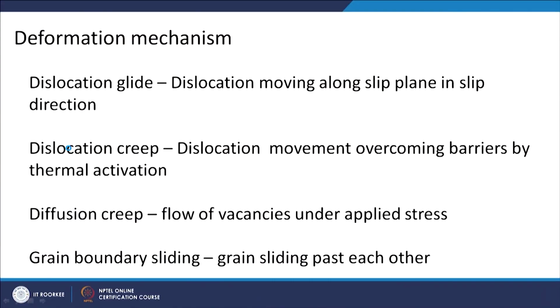Deformation mechanisms, we already have. These are the typical deformation mechanisms which take place during high temperature deformation. What we usually get at room temperature or low temperature is through dislocation glide, where the dislocation generation will take place. Then the dislocation will glide on the slip plane in the slip direction. So, this is your usual dislocation glide mechanism. This is one of the mechanisms that will always be there.